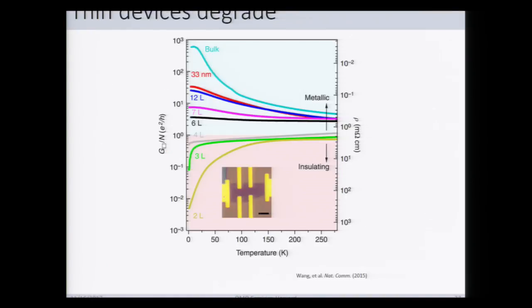And unfortunately, as it turns out, like I implied at the beginning, these systems oxidize on their surfaces. And when you have only a 2D crystal, you literally have a surface as what you're working with. And if you do normal fabrication processes, you get something like this, which I'll describe now. Here you have the conductance per layer as a function of temperature. And in the bulk compound, you see that it's nice and metallic. The conductivity rises by a few orders of magnitude as you lower your temperature from room temperature down to about 4 Kelvin. As you measure thinner and thinner samples that have undergone fabrication, you see that this temperature dependence gets weaker and weaker. And then as you go to the thin limit, it ultimately becomes insulating.